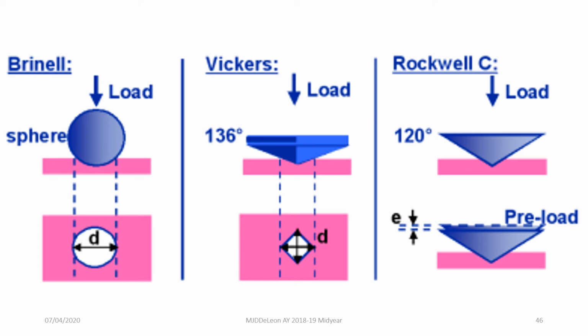So shown in this slide is just some of the quantitative ways that we can measure. We have your Brinell testing, Vickers testing, and Rockwell testing. So itong different modes na to, this essentially just indents your material with different indenters depending on the testing kung anong indenter ginagamit nila. And you can then measure the hardness from the size of the indentation or the depth of the indentation formed in your material. So the mechanism of this one will be explained to you in a higher materials engineering course.